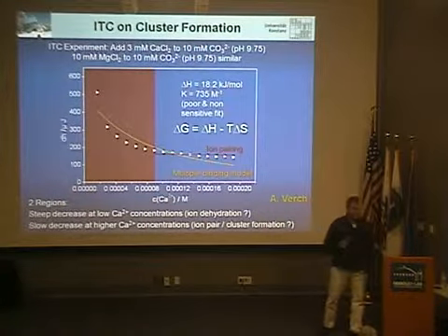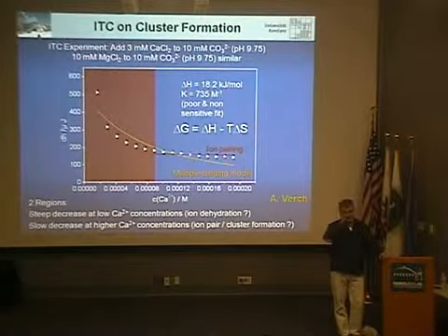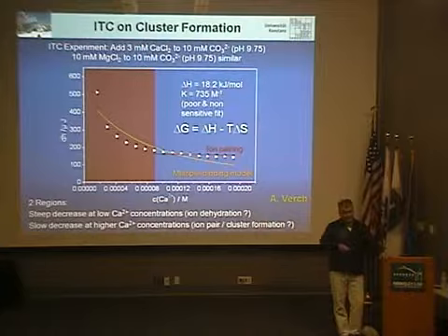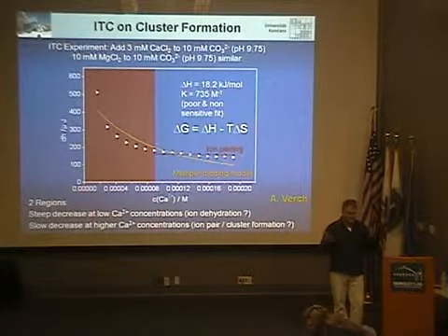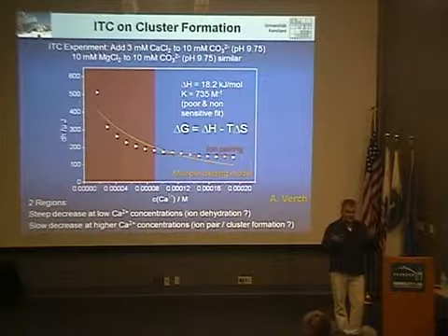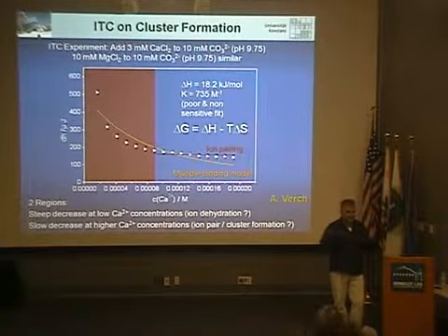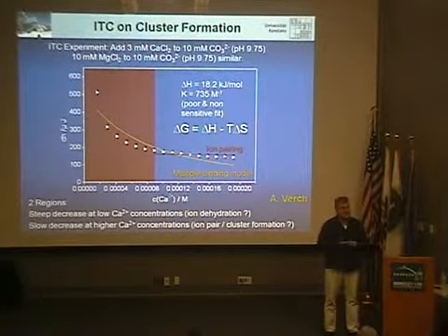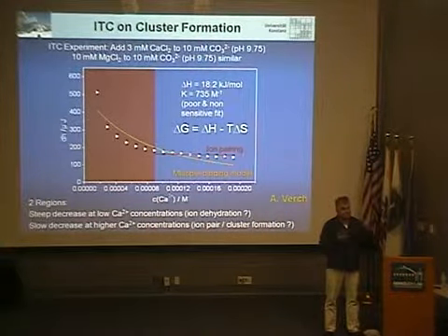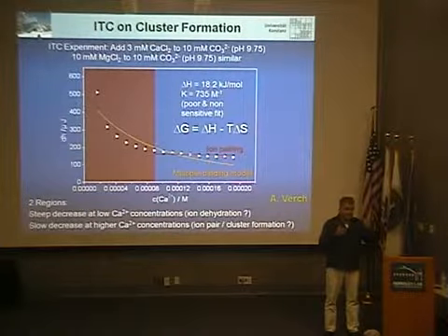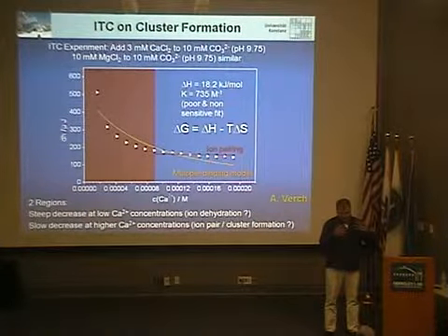Well, what you see from the titration curves is clearly that at the point of nucleation, the ion concentration drops, which means ions are consumed. So the nucleation is not only driven by the clusters, otherwise you wouldn't detect the ion drop. And if you look at the curves, calcium versus magnesium behave differently. So it's also a different importance of calcium versus magnesium to get into the mixed clusters.